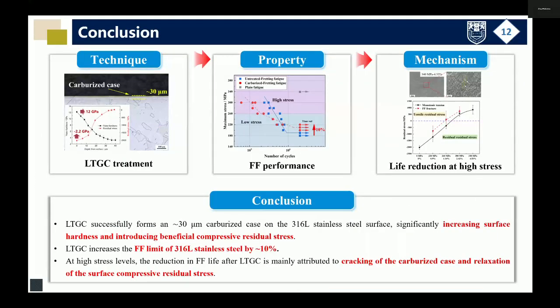Next is the conclusion slide. LTGC successfully formed a 30 micrometer carburized case on the 316L stainless steel surface, significantly increasing surface hardness and introducing beneficial compressive residual stress. LTGC increases the fretting fatigue limit of 316L stainless steel by about 10%. And at high stress levels, the reduction in fretting fatigue life after LTGC is mainly attributed to cracking of the carburized case and relaxation of the surface compressive residual stress.